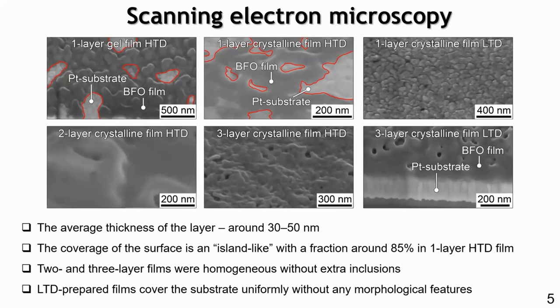It is very important that even if we do further deposition, I mean, if we put more layers on the film, we for sure can cover all the surface, but the morphology of the films becomes quite imperfect. So if you see two layers deposited, three layers deposited films, now it covers all the surface, but you see that it creates a kind of pores inside the film, and this is not really good, because these pores can, as we show later, really provide enhanced leakage current in the films.